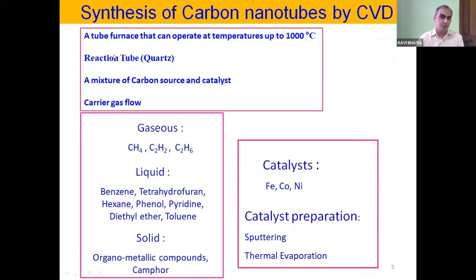Second thing is a reaction tube is required, which is generally made of quartz, and then you require a mixture of carbon source and its catalyst. Many scientists have worked on this synthesis using carrier gas flow. Carrier gas is generally chosen as argon or nitrogen because they provide an inert atmosphere within the reaction tube. All three kinds of states of matter have been applied for the production of carbon nanotubes. It is gaseous, liquid, or solid.